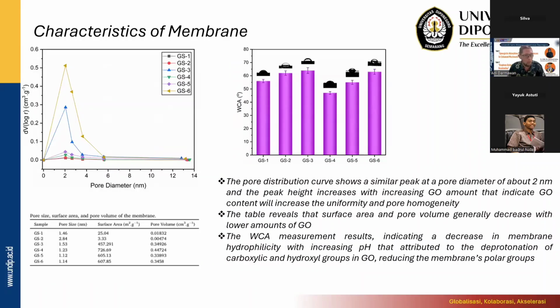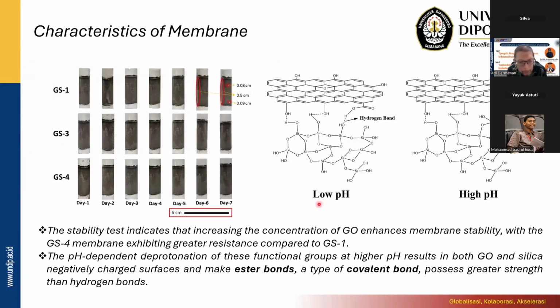And okay. This is the water contact angle. Also the pore size distribution curve shows a similar peak, it's quite the same, because we just compare between the GO and the silica. And what's the idea? This is the idea: how the GO can combine with silica. We propose that the structure is like this one. This is the silica structure, and this is the GO structure, because the silica has an OH functional group, and GO also has the OH group. So this is the hydrogen bond, between the H of the OH and the H.